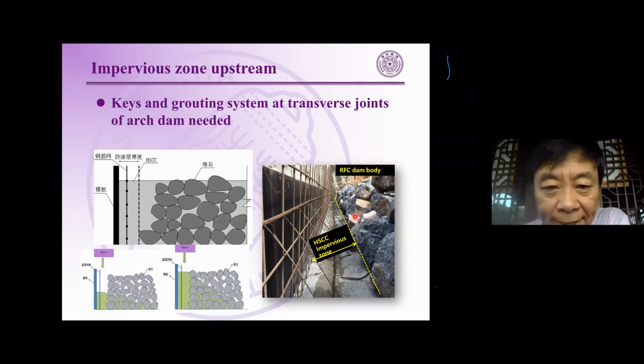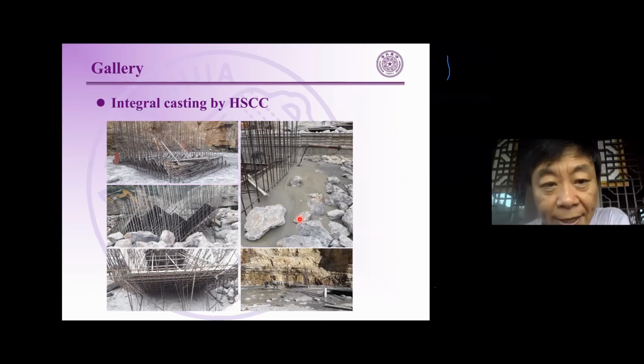And we can use galleries. You can see around the galleries, you have to set some reinforcement. And if you have reinforcement, then you can set a void. You can cast it simultaneously, or by integral casting with the self-compacting concrete. It's very easy. It's similar to the impervious zone: you have some reinforcement, and in this area there are no rocks, and then the voids and the reinforcement can be cast by high performance self-compacting concrete at the same time.